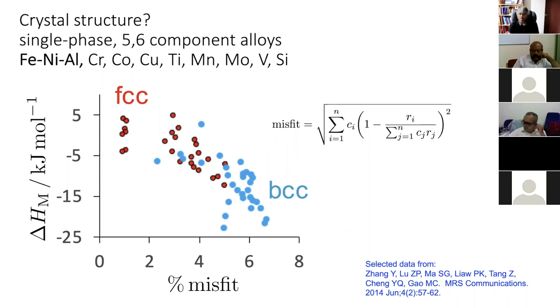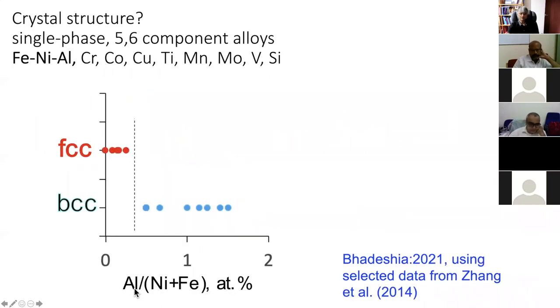So I took all of these data, and remember there's an awful lot of points here, and I did a very simple analysis where I focused just on the iron, nickel, aluminium concentrations and completely ignored everything else, even though there might be an equal amount of chromium and cobalt in this high entropy alloy. I'm completely ignoring all these and just looking at iron, nickel, and aluminium. And to my astonishment, and remember I included all of these points, when I plot against the aluminium to nickel plus iron ratio, there is an absolutely clear distinction between the FCC and BCC.